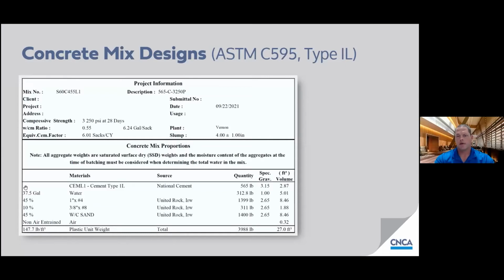Here we have an example of a concrete mix design that was produced with ASTM C595 cement, which is type 1L, which is Portland limestone cement, the main topic of our discussion today. This one happens to be a Green Book mix. You can see by the designation here, this description here at the top, 565C3250P. What that stands for in this nomenclature is 565 pounds of cement, a C, they have an ABCDE system for aggregate gradation, 3,250 PSI compressive strength at 28 days, and the P means that this is a pumpable mix. And so you can see what they've got down here is just like the description says, 565 pounds, in this case of Portland limestone cement.